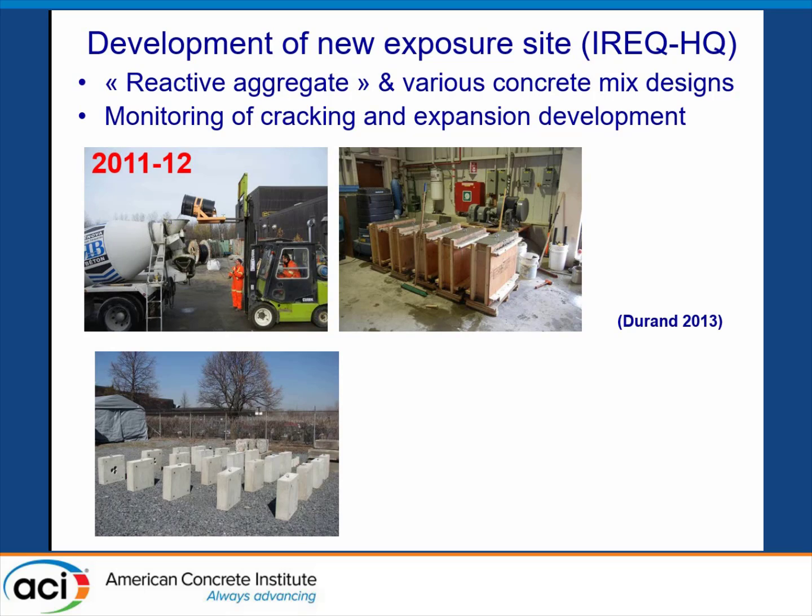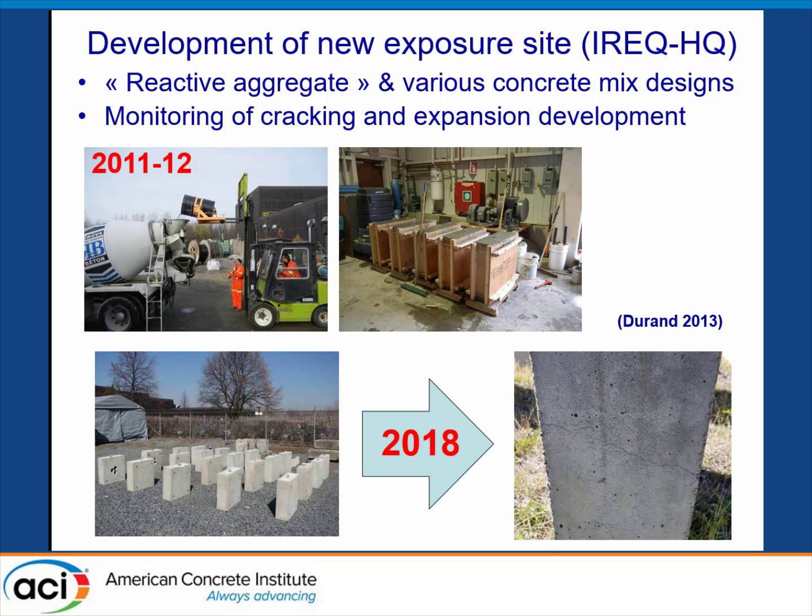We also developed an exposure site with the reactive aggregate, the aggregate from Trois-Rivières, but also other sulfide-bearing aggregate, and with different types of concrete mix designs. And we monitor the cracking and the expansion. The blocks were made in 2012, and in 2018 the first cracks appeared.